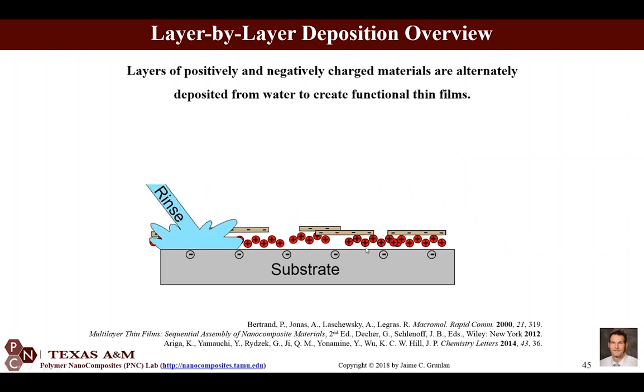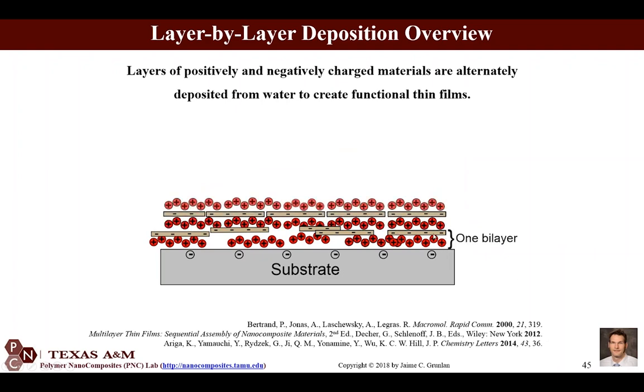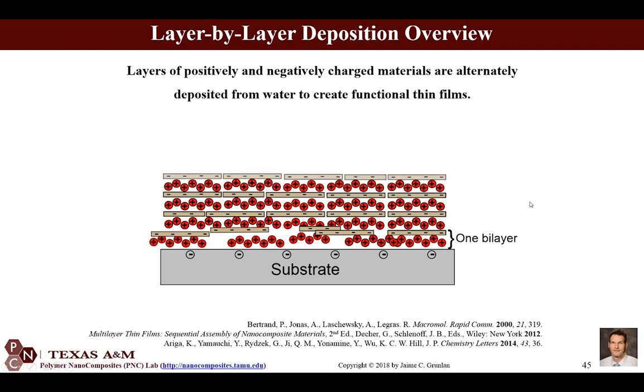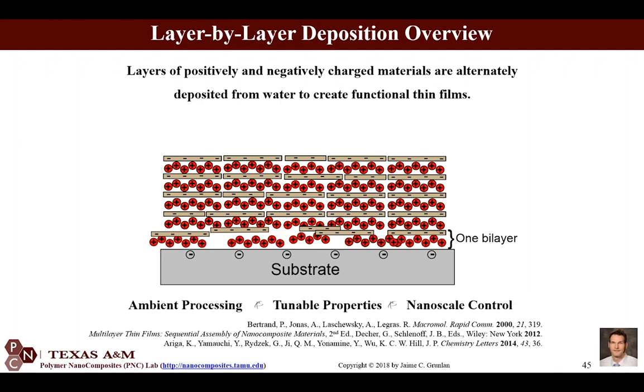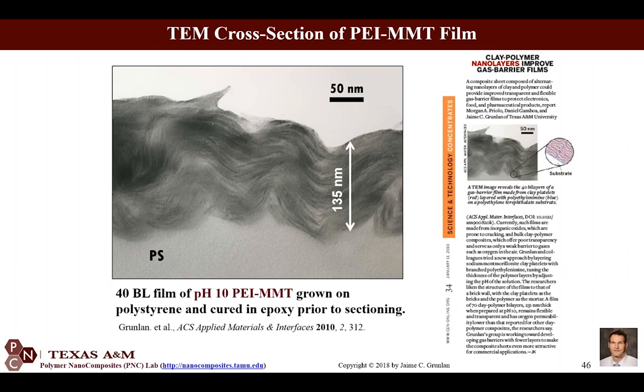In this case, you're looking at a cationic polymer being layered with an anionic plate of some type. In my mind, that's a clay platelet, which is the basis for a lot of the things I'm going to show you today. But anyway, it's a very convenient coating tool. You can process under ambient conditions, but get properties like something that's been chemical vapor deposited. Here you're looking at a cross-sectional TEM image that looks like maybe something you found in your shower drain, but it's actually 40 layers of clay with polymer in between. So we would call that a 40 bilayer polyelectrolyte film.